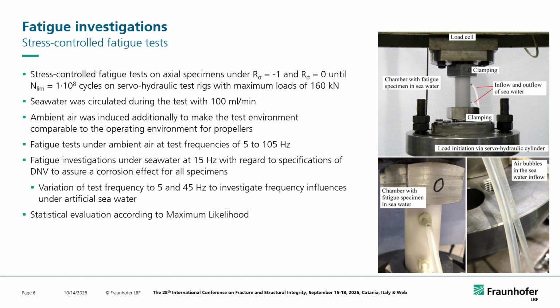Under ambient air, it was not really the problem, and depending on the load level that we tested, we could use test frequencies between 5 Hz for the really high levels to prevent some warming of the specimens. Nonetheless, in this level and fatigue level, we are talking about the medium cycle fatigue range. Probably those specimens under 5 Hz ran for 50,000, 60,000 cycles until failure. And on the lower levels under ambient air, we went on electro resonance test rigs up to 105 Hz.